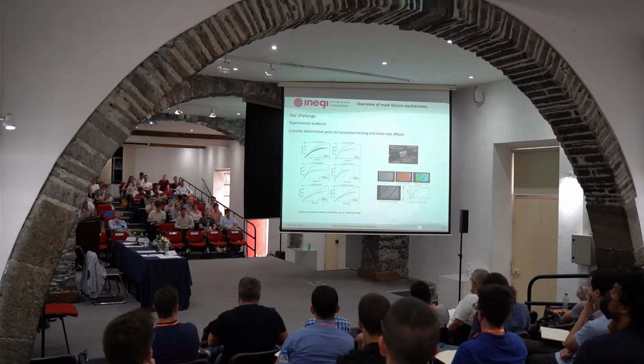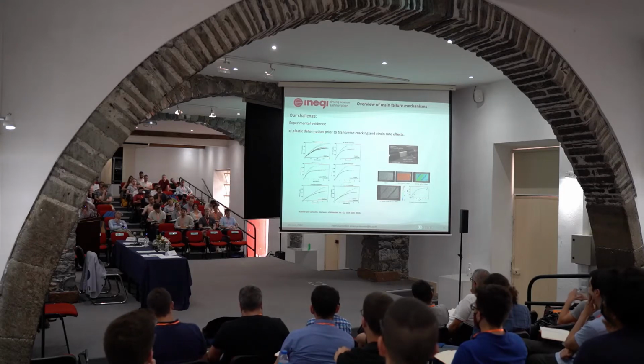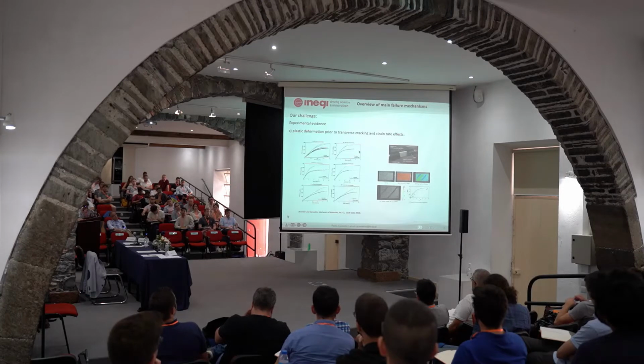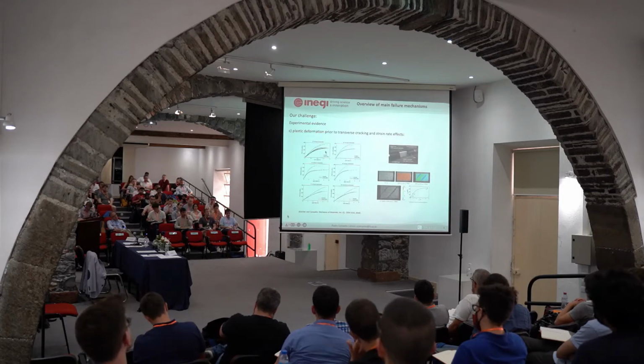Okay, now also of course we have a viscoelastic matrix, so we have viscoplastic effects prior to transverse cracking and of course associated strain rate effects. And here what we did, again, was to perform off-axis tests, but we performed them using a split Hopkinson bar and a standard test machine, so a different strain rate range. So from quasi-static loading all the way to 300 and at a later stage 1000 deformations per second. Now, what we can see here is the relation between the stress and the strain for quasi-static and for dynamic, okay? And you can see that you have this non-linearity that depends on the strain rate that you apply.